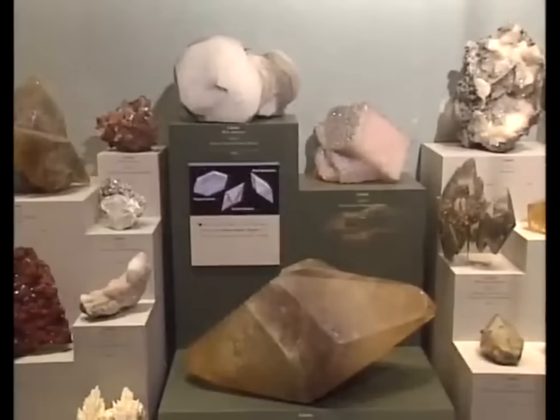So how is it that one mineral can look all these different ways when it forms its crystals? The shapes of the calcite crystals depend on a number of different growth conditions. For example, the temperature under which they're growing, the concentration of the solution from which they're growing, that is, how many atoms of calcium carbonate are present in that solution. It also depends upon the composition. It may depend on whether impurities are present in that solution. All of these different factors come together to influence the shapes of the crystals. Crystals are very sensitive to their growth conditions.